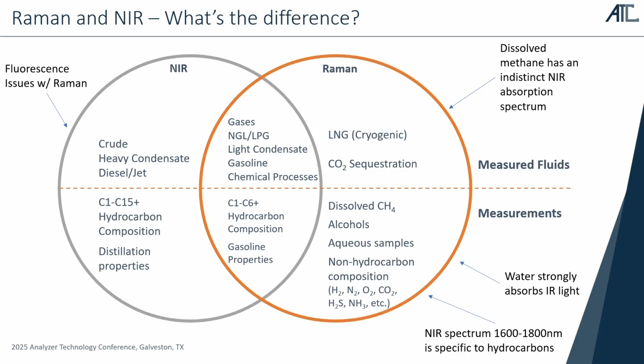But for NIR: crude and heavy condensate, diesel and jet fuel, I would say NIR spectroscopy is a good option for those measurements. Because with strongly colored or, in the case of crude oil, black samples, Raman measurements show a whole lot of fluorescence. And fluorescence is when your laser light hits the sample and the light is scattered back at a longer wavelength, but it's not the Raman kind of scattering. It's a different mechanism, and it interferes with the Raman spectrum. There are easy ways around that with pre-processing the spectra, but it is a source of noise and interference that, if you can avoid it, you might as well. So for heavier, darker colored hydrocarbons, NIR probably makes more sense.